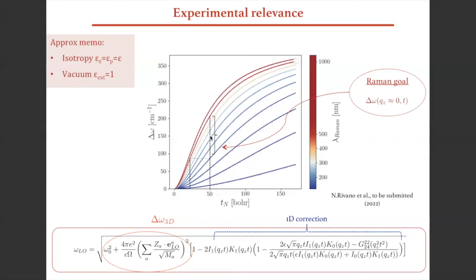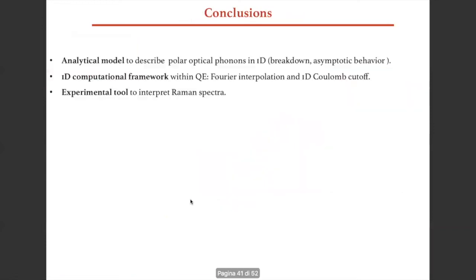So the idea is that once we are able to parameterize this formula fully, for example, having some reliable data about Born effective charges, masses, dielectric properties in general, mechanical splitting, and so on, our model is able to give exactly the size of the dielectric shift in terms of the size of a material. And so we can predict the position of the peaks, or, starting from the position of the peaks in the Raman spectra, understand what's the size of the material we are studying.